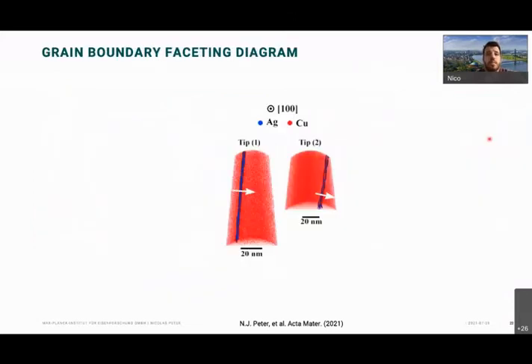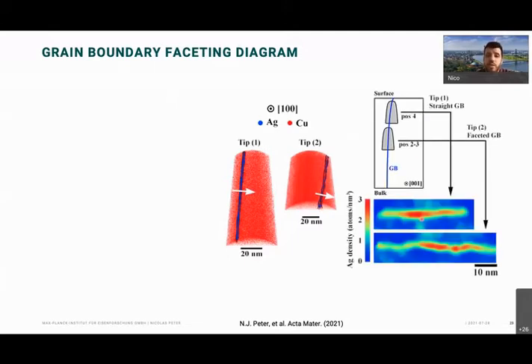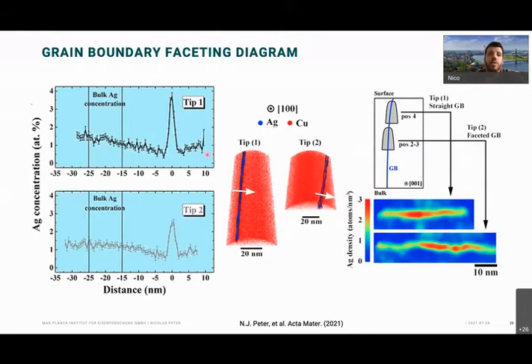Again, we did some APT measurements. Again, we find silver being segregated only to the boundary. We also found, for the one tip that was closer to the surface, a straight boundary, and for one deeper into the material, a faceted boundary. And also we could observe again our enrichment at the boundary with a depletion zone close to the boundary, until it reaches in the bulk somewhere again the equilibrium or saturation value of silver.